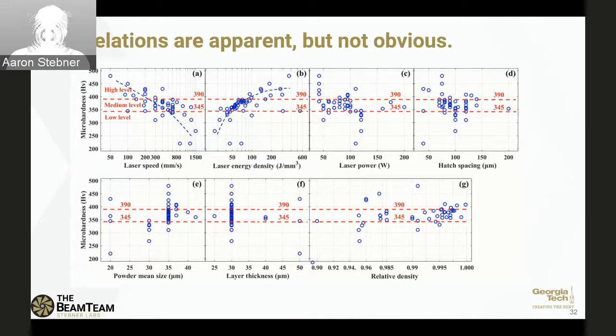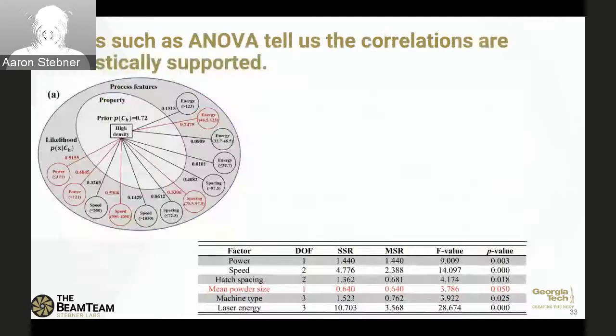And so here in A and B and even C, they're not necessarily linear trends, but there are definitely trends in the data in terms of high hardness to medium hardness to low hardness versus these different parameters. And once we feel good about that, we can go to the next slide and perform more rigorous statistical tests such as ANOVA to actually tell us how strong these trends are and if they are statistically significant in the higher dimensional space. And so we do this for each of the different classes. So we take all the classes of the inputs and look at them relative to each class of the output. And then we repeat this in this case five times and make sure that each of the models we're going to want to build are statistically supported by the data. And so let's go to the next slide.